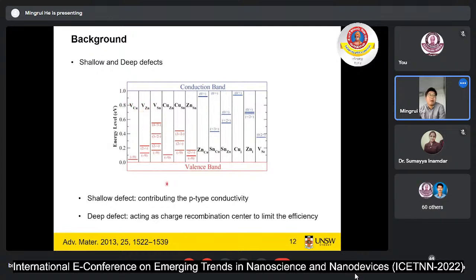On the other hand, there are the bad defects, like deep defects. For example, mid-gap defects like tin vacancy defects or some tin zinc anti-site defects can act as charge recombination centers to limit the efficiency. So here is also our task, to resolve this problem.